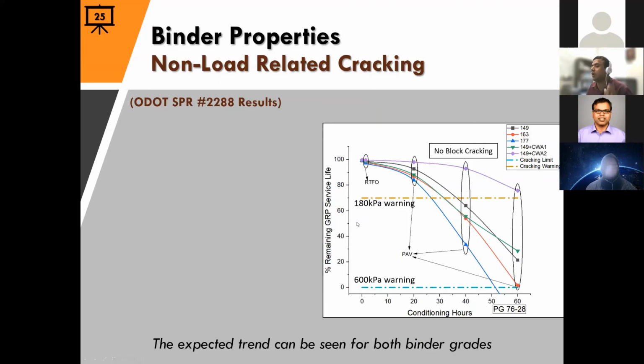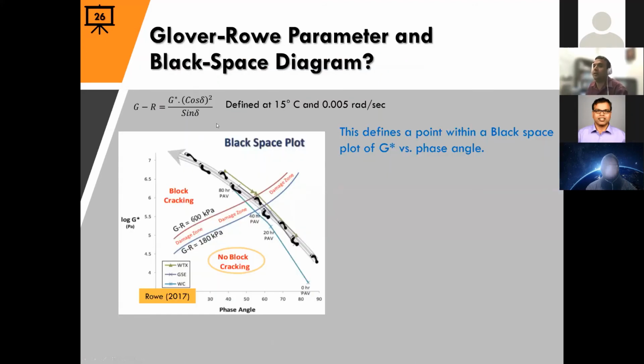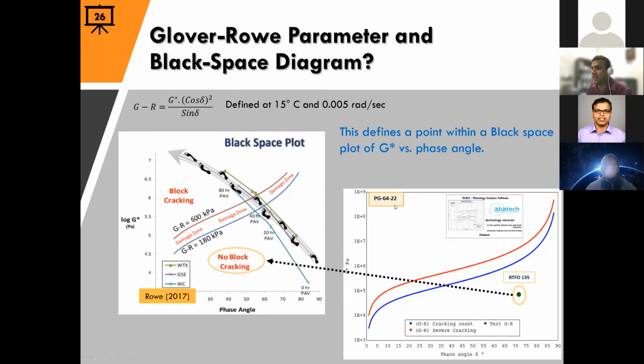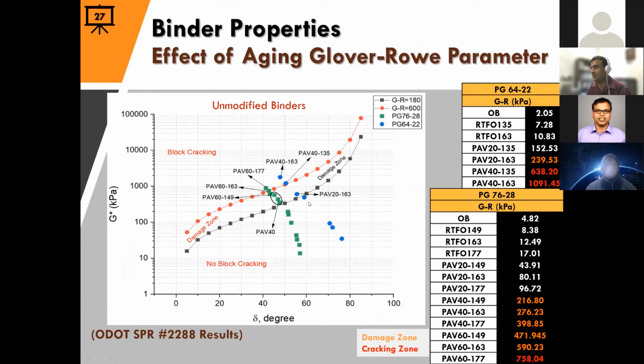We are basically talking about the whole warm mix asphalt technology, and it's really working well. This is another way of doing this. This is called Black Space diagrams. Again, G* over phase angle against phase angle, and there are zones where the material lies. And if you look at it at RTFO 135, this material lies in the no block cracking zone. I'm going to just show this one plot, and then we'll try to summarize.